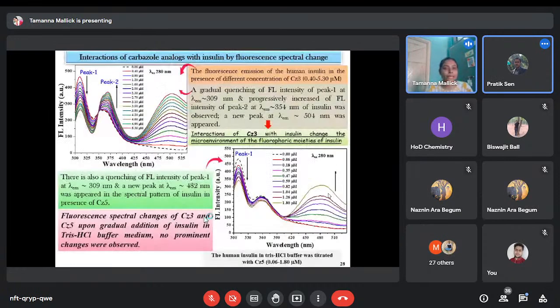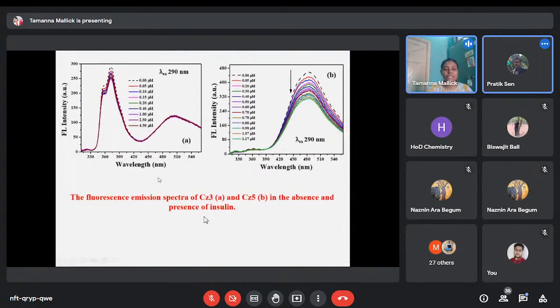Hence, we are very much interested in the interaction of carbazole analog with insulin by fluorescence spectral change. This is the fluorescence emission of human insulin in the absence and presence of different concentrations of CZ3. Here, with progression of the addition of CZ3, peak 1 gradually diminished and peak 2 gradually enhanced, and a new peak arises at 504 nanometer. A similar experiment was done in case of CZ5, and the fluorescence emission spectra of CZ3 and CZ5 in the absence and presence of insulin were observed here, but no special change was observed.